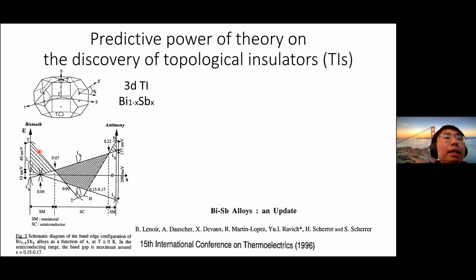Here different lines label the energy of different bands. When two lines cross, that means the two band energies cross. By looking at how these band energies cross, and just based on that information, they identified a region where they believed was a topological insulator.